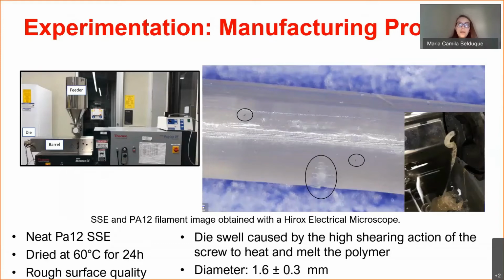Okay, so the first material being extruded is nylon 12, to find the conditions needed to adequately process the composite. Prior to processing, the nylon 12 was dried in a conventional oven at 60 degrees Celsius for 24 hours. Although every parameter was very carefully monitored, the material started swelling, as shown in the right image. Different temperature ranges were tested to achieve a continuous extrusion, but the problem persisted.